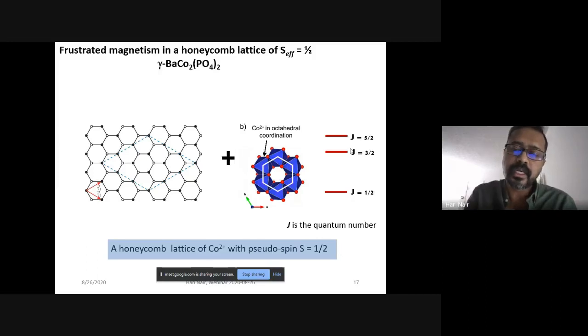So it is the direct effect of the Stark effect, and the atomic levels of cobalt would split up because it will remove its degeneracy, and the ground state would be a J of half separated from the next highest level of 3/2 by a very high margin of energy. So you can consider that J as an effective pseudo spin of half. So that makes it an ideal constitution. We have a honeycomb lattice of cobalt, we have a quantum mechanical spin half, and we have geometrical frustration. So this could be an ideal situation to study if it forms a quantum spin liquid or if it has some fancy excitations, anyons, things like that.